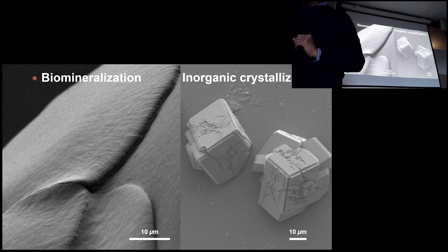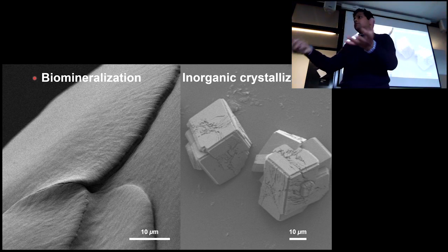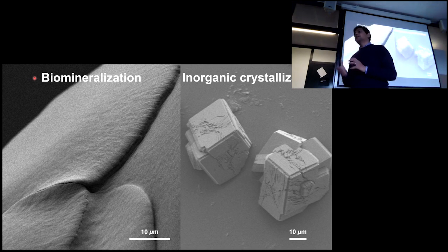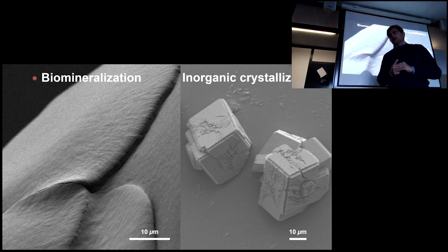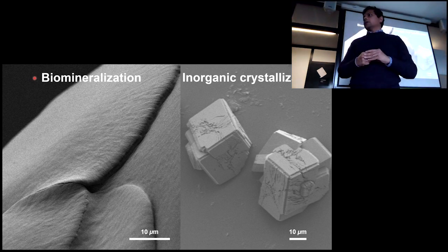How do you stop the formation of these layers? Does it run out of calcium, basically? Yes, it runs out of calcium, or you quench it by just taking the chitosan from the solution. But then there is the risk of incomplete mineralization. So you will have spots where no calcium carbonate films form. But there are ways that we try to overcome that.